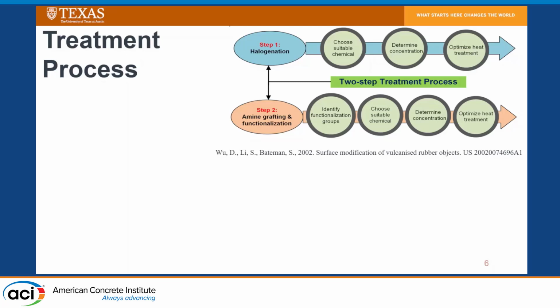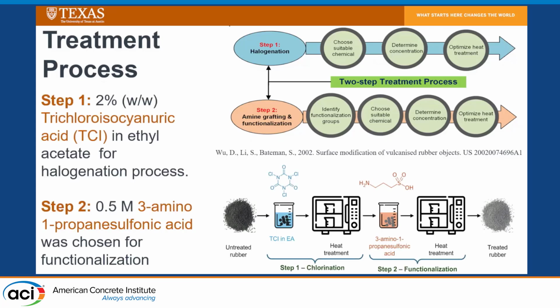So after in-depth study and preliminary studies, Sanjita had identified two different chemicals to use. The first one is TCI in an ethyl acetate solution. In this first step, the main goal is to try to improve the hydrophilicity of the rubber. And then the second step was mainly to graft on these amine functional groups. Primarily, she selected these in order to have good bonding with our particular matrix, in this case, cement. So over here you can see our finalized process. We had our untreated rubber. We did the first step of the process.